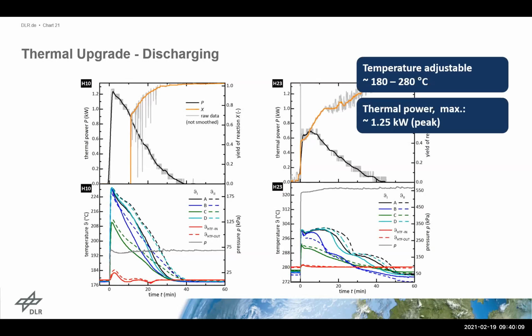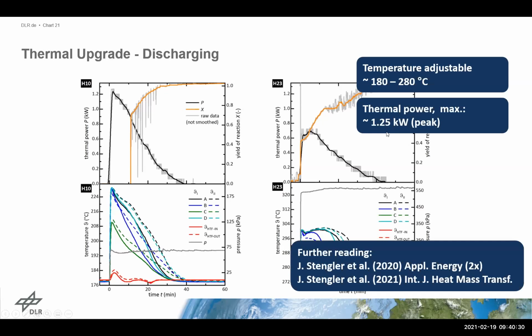So summarizing all our discharging experiments, the temperature is adjustable, as I said, from 180 to 280 degrees Celsius discharging temperature. So in principle, we can have 100 Kelvin of temperature lift inside of our thermal store without any additional pump. The thermal power is more or less the same like for the charging process. For further reading, my colleague Jana Stengler, she finished her PhD at the end of last year, and she published two, from my understanding, very interesting articles, in Applied Energy in 2020, and very recently also one in International Journal of Heat and Mass Transfer. So if you are interested in that, please have a look.